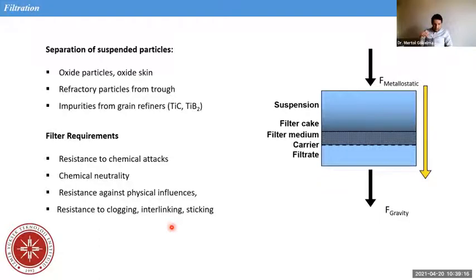Depends on the pore size or the type and the flow. There can be clogging, and this is also not wanted. So it decreases the efficiency a lot. But one of the most important is the chemical attacks, because aluminium can easily attack many oxides. And if you use metal, aluminium easily dissolves many metals.